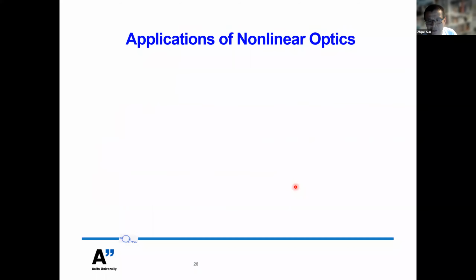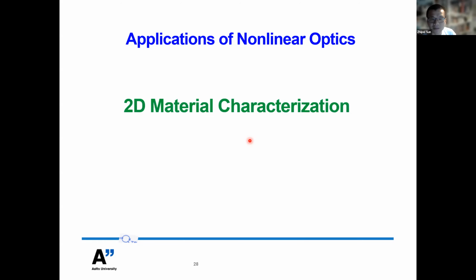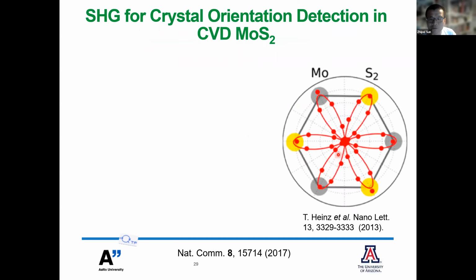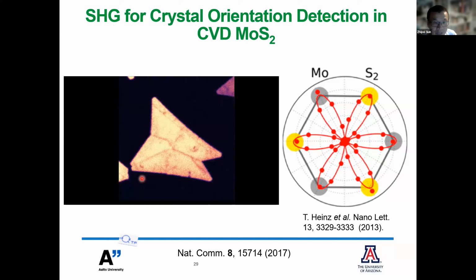Before I go to the integrated photonics that we are currently working on, we have already used nonlinear optics inside 2D materials for their characterization. For example, if we go back to the second harmonic generation of MoS2, the polarized second harmonic generation response of MoS2 is patterned. This is due to the crystal symmetry of MoS2. Therefore, using second harmonic generation, you can estimate the crystal orientation of the flakes. Here, I would like to show you one video.